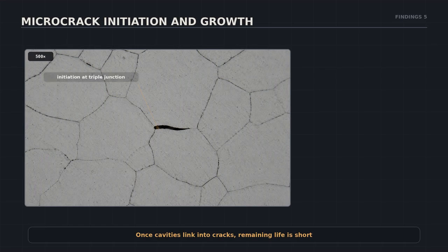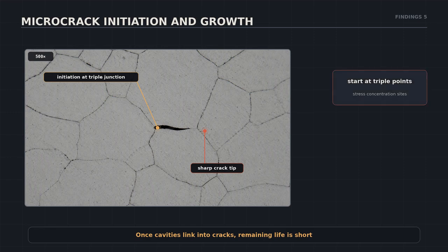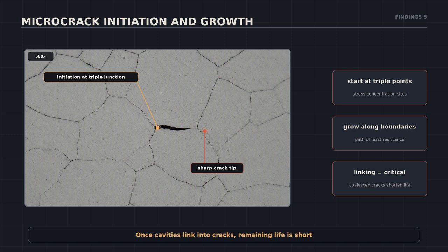When coalescence goes far enough, microcracks form. They initiate at boundary triple points, grow along the boundaries, and link into networks. At this stage the damage is no longer theoretical, remaining life is short, and the finding drives a formal assessment. This is exactly why the earlier stages matter, catch it at cavities, and you never see this picture.